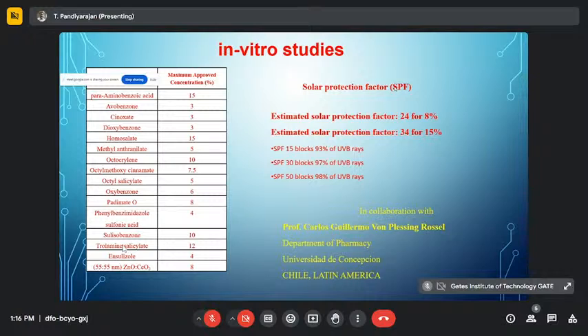It's called SPF, and we found that an SPF of 24 was achieved for 8% of the prepared material. If I increase that 8% to 15%, then the sun protection factor increases to 34. Basically, in the supermarket, when you see UV sunscreen creams, they specify SPF 50, SPF 30. What does it mean? Next time when you go to the market, you will see SPF 50.